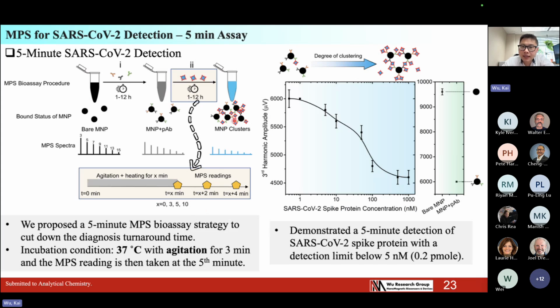So as we anticipate, the analyte will cause the clustering of the nanoparticles, which will lower down the harmonic amplitude. You can see from the figures on the right side, as we summarize, as we increase the SARS-CoV-2 spike protein concentration, you can see a drop of the harmonic amplitude forming the almost linear curve or S shape. So this gives you the detection range of this biosensing platform from sub 1 nanomolar to over 1 micromolar, and also a linear range of detection of this biosensing platform.